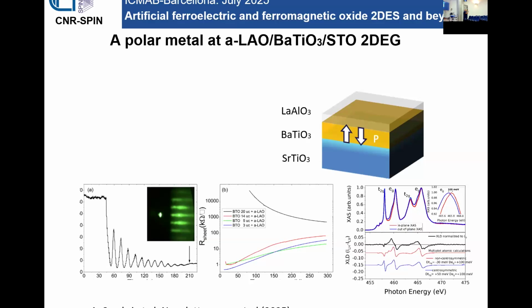With barium titanate, I don't know, because we could not do the switching. Maybe I should do an experiment trying to switch the polarization, but it's not easy because you have to switch from the top. Experimentally it is challenging. With calcium-doped strontium titanate, I can tell you that at least there are dipoles that we switch in a non-volatile way, because we see a non-volatile change of the orbital splitting, of the titanium 3d splitting. But it's not full, you just change a little bit. So the polarization still has one direction, and you don't change it completely.